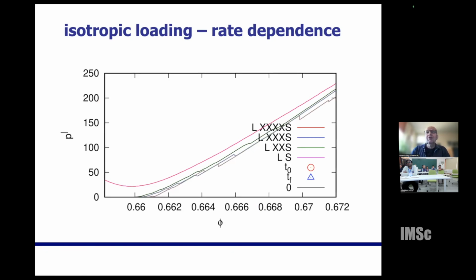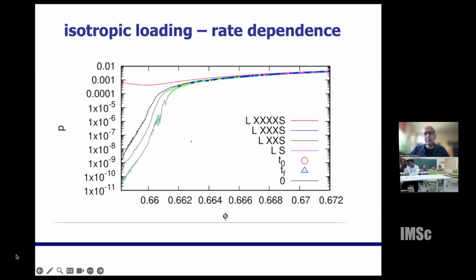And that's what I meant when I said you have to go really, really slow to see the phenomenology which I was talking about. Okay, and you see, fast rate, very smooth. The slower you go, the sharper these plastic events get. And then you can analyze them if you have them. With the magenta, with the fast simulation, you never can see the plastic events. Pressure in logarithmic scale as a function of density. And very low pressure means we have no elastic contribution. And here the elastic contribution starts to kick in. And at very high density, there's no rate dependence anymore, because the rate effects are negligible as compared to the elastic effects.